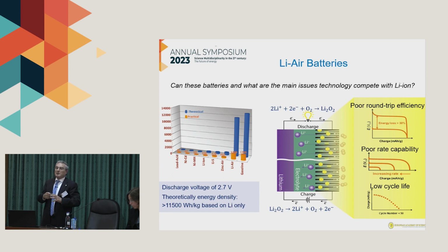Lithium-air batteries are the best batteries from the energy density point of view. We can see here that the theoretical energy density is approximately 12,000 watt-hour per kilogram on lithium only, with a discharge voltage of 2.7. It's quite similar to gasoline in theoretical and experimental terms. What is the problem? These systems have poor efficiency, poor rate capability, or low cycle life. As I said before, we need at least 30 years to move to this technology, which is the most competitive technology from the energy density point of view.